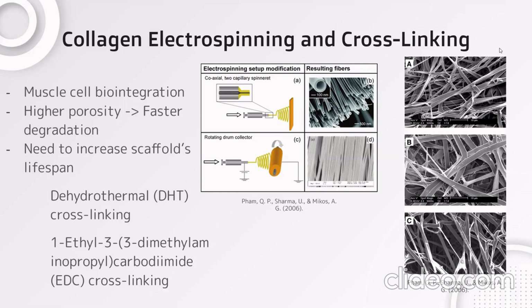So we need to increase the scaffold's lifespan. To do this, we use DHT cross-linking, which stands for dehydrothermal cross-linking. This process involves heating the collagen past 90 degrees Celsius under a vacuum. It's non-cytotoxic, decreases inflammation around the implant site, increases cellular attachment, and provides much higher strength. Unfortunately, cross-linking decreases biointegration with cells, but is necessary, especially because of this higher strength. Nonetheless, we have to do it, and it also increases the lifespan, so it's very important.